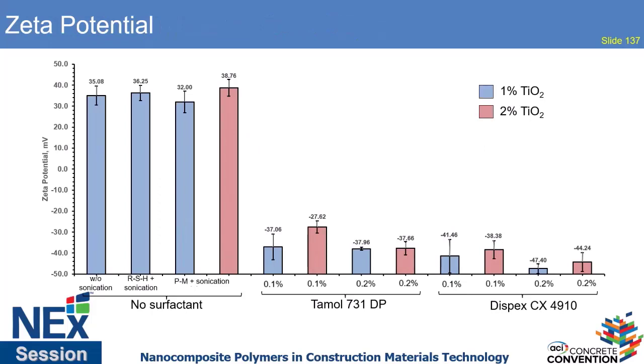And the zeta potential was the last thing that we were measuring, which is basically a measure of the electrostatic repulsive forces. If no surfactant was used, we got a positive zeta potential, and with the surfactants, we got a negative zeta potential. Zeta potential is a very important check when you're trying to do electrostatic stabilization. However, many people rely just on the zeta potential, and zeta potential on its own is not sufficient.